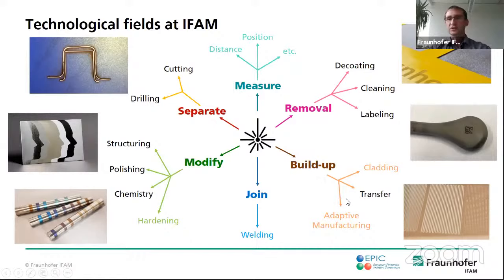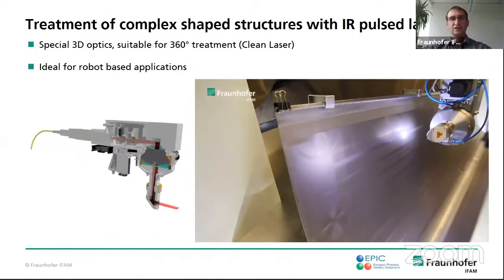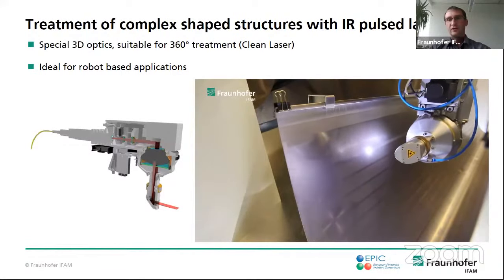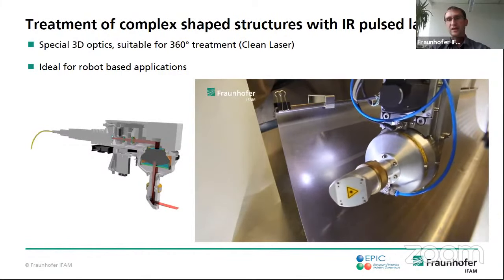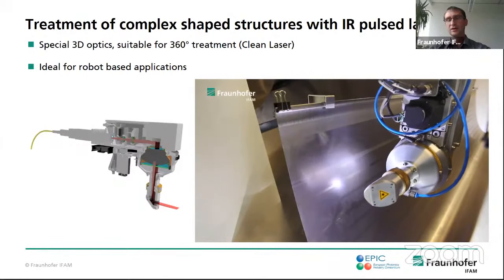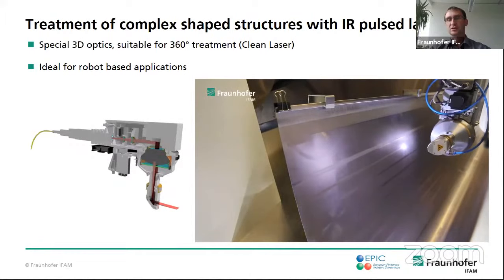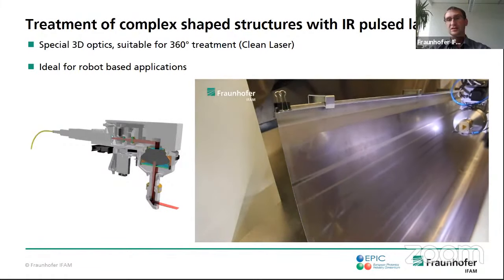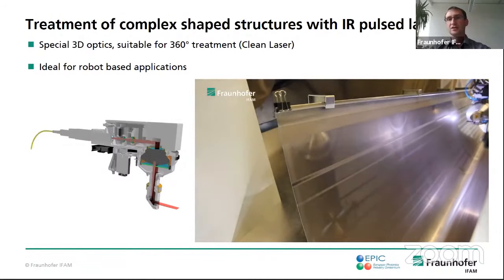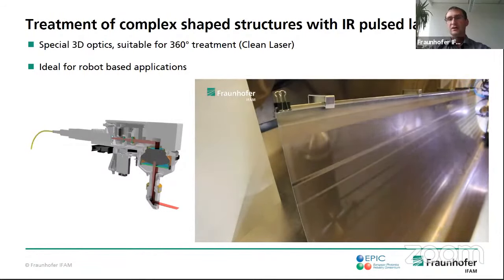Not all of these applications we are doing with a UV excimer laser, but another example is shown here to the bottom left. So that's a coloration of titanium. We are modifying the surface oxide layer, and thereby we get a color labeling of the substrate material. Some of the applications that are shown here, we are also applying IR lasers. Just to show an example here, that's a very special 3D optics with a 360-degree mirror head at the end of the optics. And thereby we are able to do a treatment of three-dimensional structures, also large-scale structures. So in this case, the part you can see here is 2.5 meters long. And again, we have here a robotic treatment.